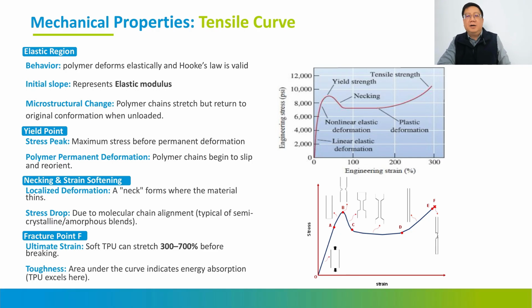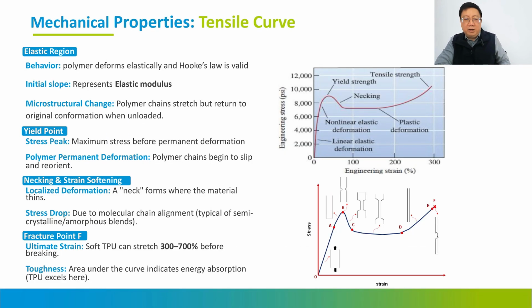If you stretch the aligner too much, past the yield point, it will not come back anymore. But if you have elastomers, whether outside or in the middle, you have very good resistance to deformation. You can check it by yourself. When you have an aligner, or make some aligner product, you just twist it 180 degrees, then see how fast it comes back to the original shape, and whether it deforms or not. If you have a good material, you can see almost no change or no deformation of the aligner.